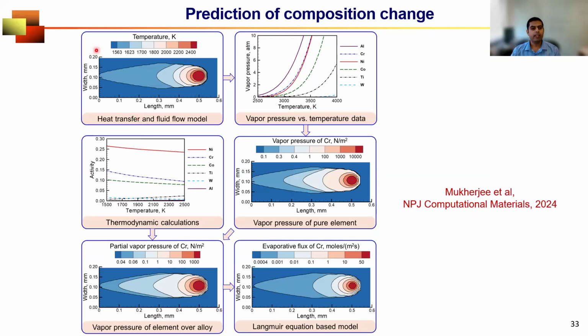So what we did, once again, we started from very basic temperature calculation. And then we know the vapor pressure versus temperature relation, and this is a material property. For different elements, we see different plots. It does not depend on whether it is additive manufacturing or welding. It's a material property. So based on this relation and the calculated temperature field, we get the vapor pressure distribution. And then in an alloy, we have different compositions of these alloying elements. Depending on that, they have different thermodynamic activity. So thermodynamic activity and vapor pressure give you partial vapor pressure, which is responsible for evaporation. So once we can calculate the evaporative flux of individual elements, we can calculate the final composition change.